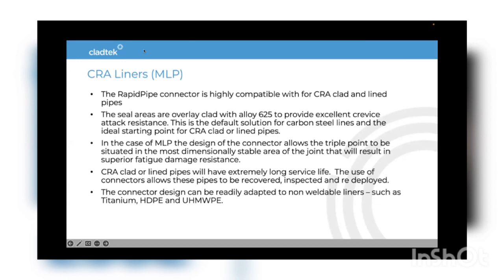But the other benefit of being able to reuse is that a carbon steel pipe at the end of its life is going to have used its corrosion allowance, etc. So it's unlikely to be redeployed. Whereas, as I said, a CRA pipe that's been properly designed and installed at the end of life, save for potential erosion from sand production and things like that, we'd expect it to be fairly close to new condition. So the possibility of reusing is very, very realistic, particularly for things with short field lives.